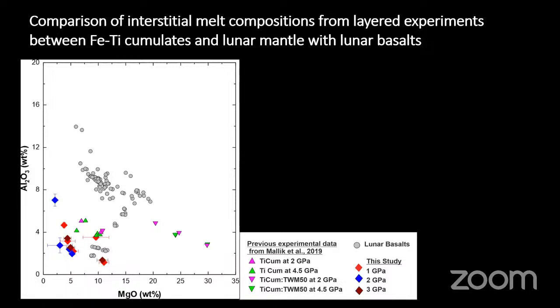This might be caused by the bulk composition that we assumed for the Moon when we formed our LMO crystallization experiments. When we decided which experiment to follow, we considered the experiment where the bulk composition taken was similar to that of the Earth. There is another possibility of a bulk composition of the Moon that is much more enriched in aluminum, about 1.5 times enriched. So that might be the reason why the aluminum content in our melts is much lower than that observed in the lunar basalts.